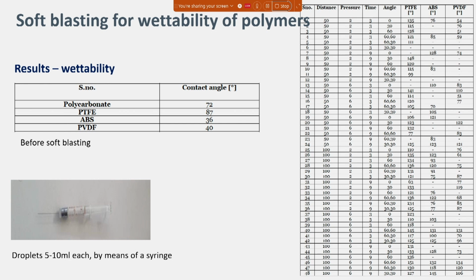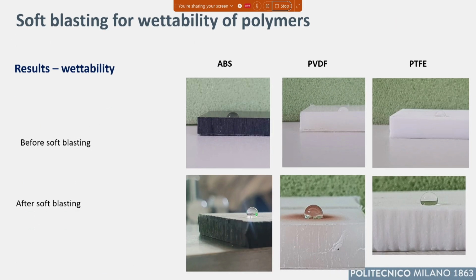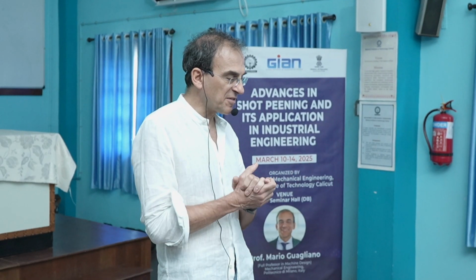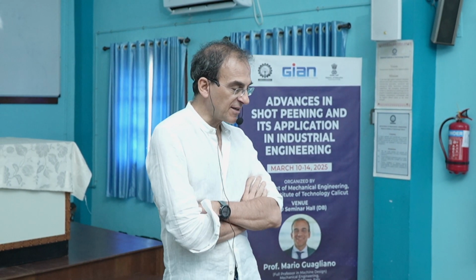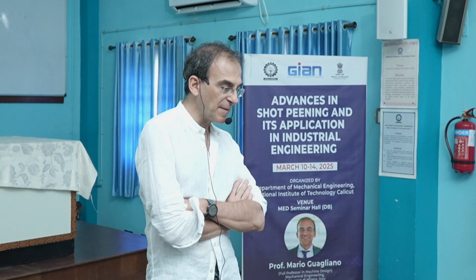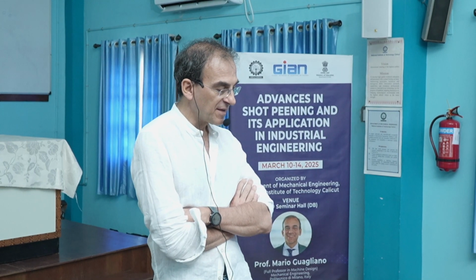And this is the test we did for assessing the angle according to the different treatment condition that we have investigated. And the result are these, considering the material ABS, PVDF, and PTFE. These are the results before and after shot peening. If we consider the situation before shot peening, it can be observed that they are hydrophilic. That is to say, the angle is clearly less than 90 degrees. But if we consider what happened after some soft blasting, at least in this condition, we see that the behavior is quite different. The behavior is hydrophobic or could be also super hydrophobic because the angle is around 150, let's say.